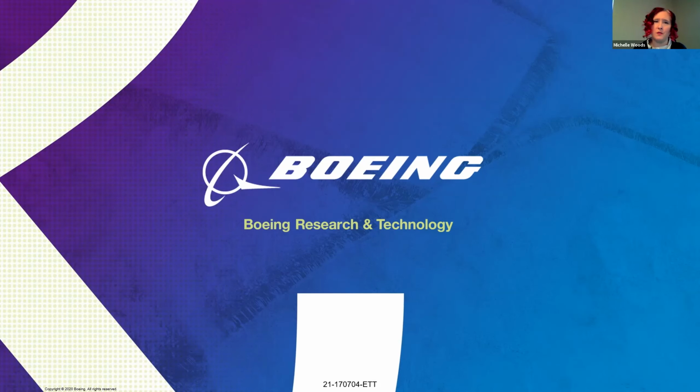Ooh, so I kind of feel like that would actually be a combination of the two things that I was talking about with the functional groups or the wipe-on treatment. Based on my background in polymer chemistry, I would say that it is a theoretical possibility that we could add those on. It would most likely look like some kind of addition to the polymer chain itself. Basically what we want is, regardless of how we get there, a more polar surface for the adhesive to bond to. So whether it's via surface treatment or functional groups that are added onto the polymer, as long as we have a more polar surface, we will have better adhesion, and that's really what we're looking for.